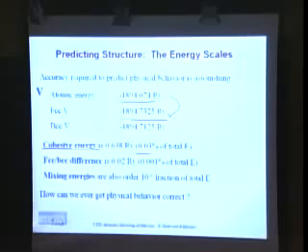Let's say you want to know whether vanadium is FCC or BCC. You could calculate it as BCC. Now the FCC-BCC difference is only 0.001% of the total energy. And these are not complicated structures. So in many cases, we're going to work with energy differences that are fractions, 10 to the minus 6, 10 to the minus 7 times the total energy. It's telling you something about how much numerical accuracy you need.